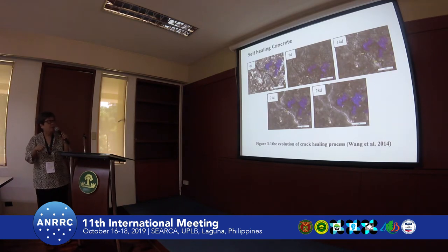This is an example of what we call self-healing concrete. And the strategy here is that if you produce your concrete, you embed your microorganisms in pellets, and you embed it in the concrete so that when a crack occurs, the crack will sever where the microorganism is embedded, and then the water that comes into the crack will release the nutrients in your pellet, so that the pellet now becomes liquid, it's available for the microorganism, and the microorganism is a spore former. That's why it can survive for a long time. So when the nutrients and the spores germinate, then the microorganisms are able to grow. And thus, if you have a crack like this, after 28 days, the cracks have now been filled. Okay, so those are future plans.